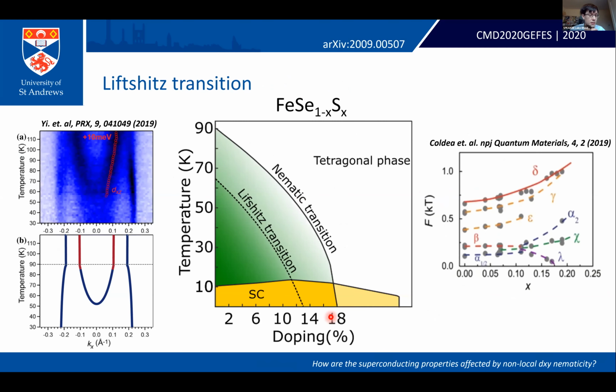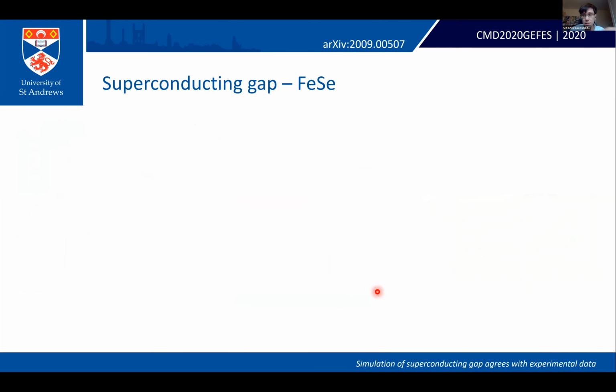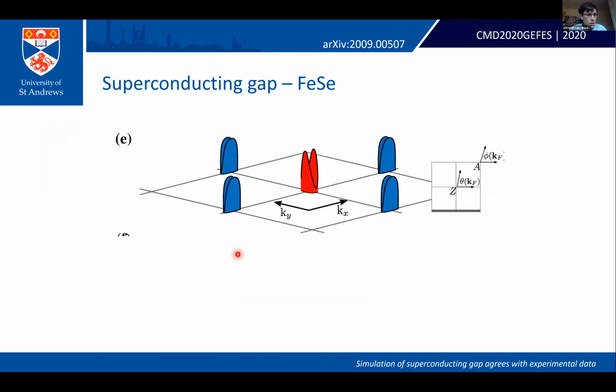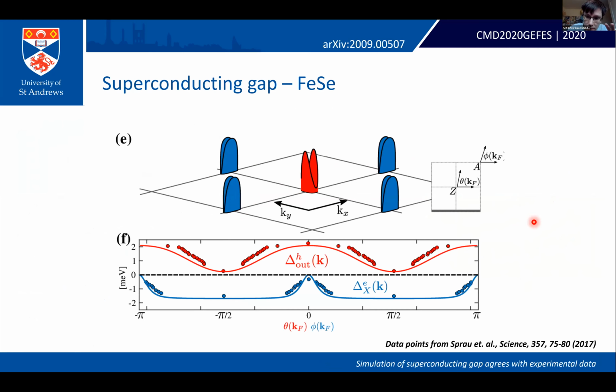Okay, so in the final couple of minutes, I just want to talk briefly about the superconducting properties of this system and how this non-local dxy nematicity would affect the superconducting state. So what we've done is we've simulated the momentum dependence of the superconducting gap of this model, assuming some spin fluctuation mediated superconductivity. The result is that we obtain a highly anisotropic momentum distribution that has a sign change between the hole and the electron pockets. And this momentum distribution directly reproduces the experimental data as determined by STM and ARPES.